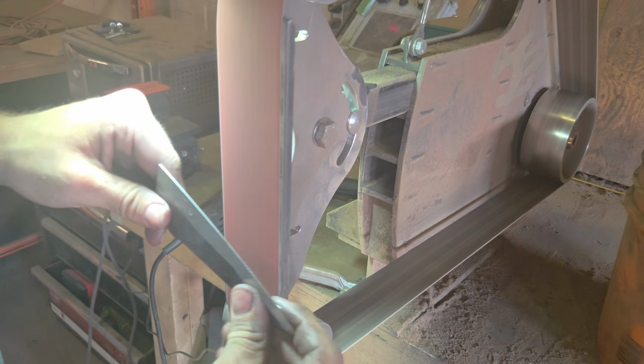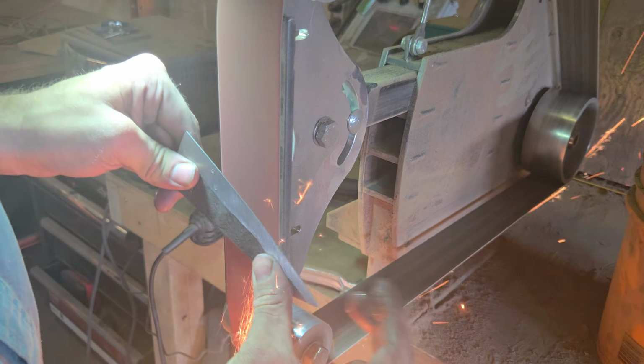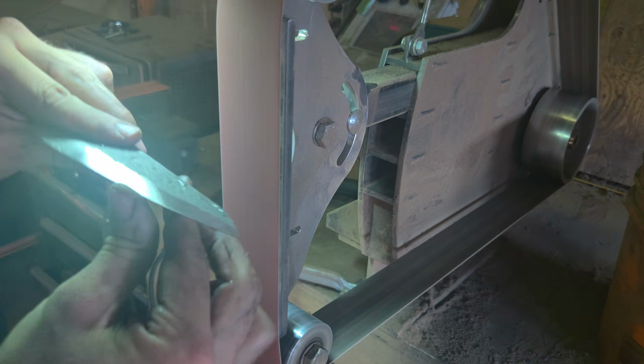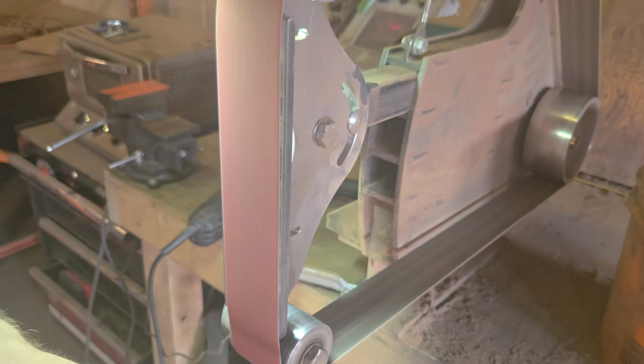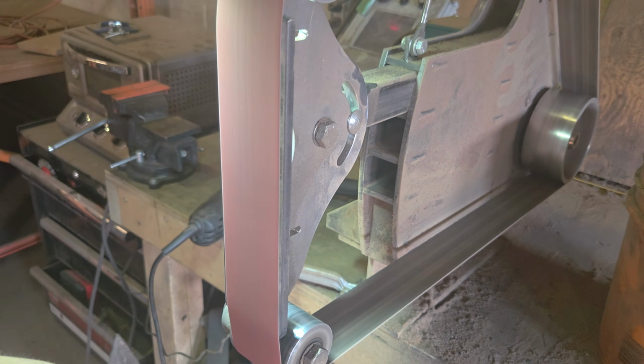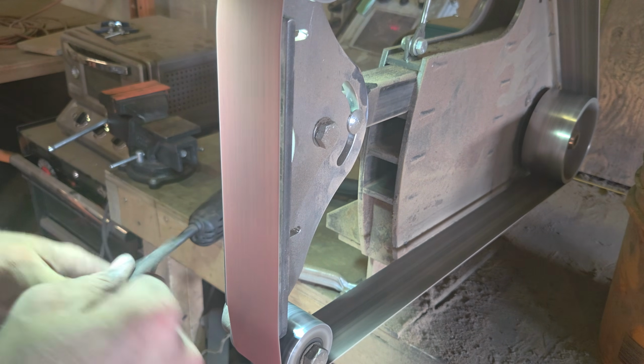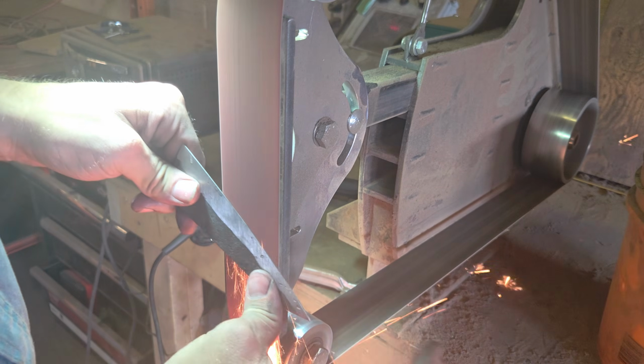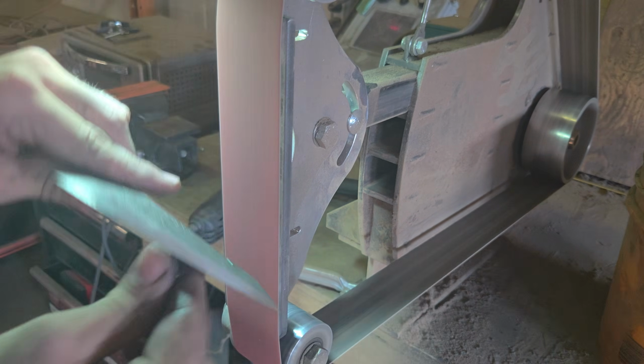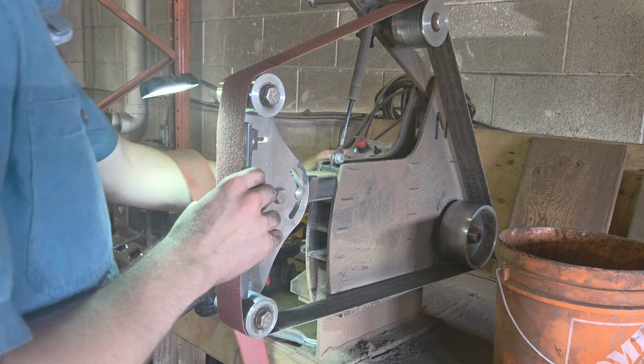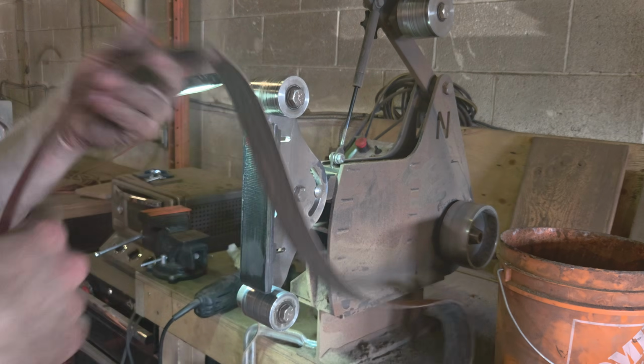When you grind a knife with a distal taper, you have to account for that taper by lowering your angle as you grind towards the tip. So for my first rough grinding stage, I just keep the same angle and get the edge closer down. But then once I do that, I have to start lowering the angle towards the tip to make the shinogi line even across the blade.